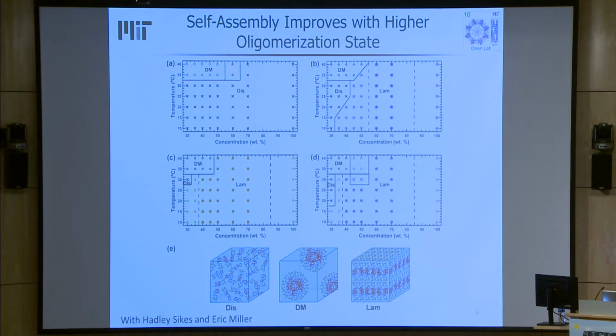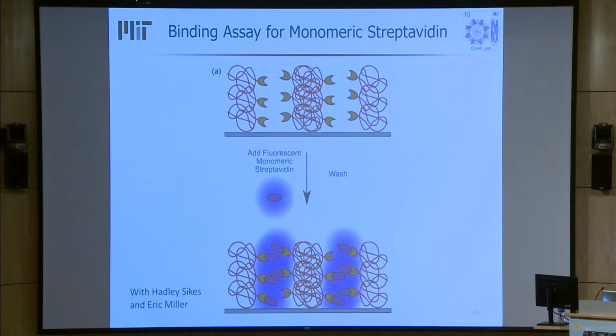The advantage of working with these small molecule binder proteins is, of course, you can get very, very high densities of active binding sites and potentially big jumps in intensity. We started in this project with an example protein from Professor Sikes' lab that just binds monomeric streptavidin. We fabricated our block copolymer layers on surfaces using these different materials and bound them with monomeric streptavidin to show selectivity. Here the selectivity is very, very high for just this one protein.